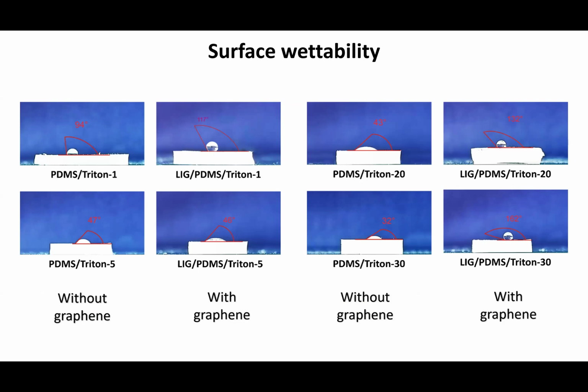One interesting thing to note is the wettability of this surface. So we tested that by putting a drop of water on these surfaces. If you focus on the bottom right two images where it says Triton 30, you see that without graphene, so this is just PDMS Triton, if you put a drop of water on that, it just spreads across the surface. You get this angle of 32 degrees.